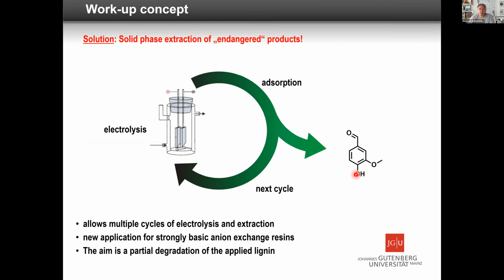The last part is definitely devoted to this. We make a conversion, we have a significantly low conversion. That means, okay, we can go up to 15%, but the problem is there are still some building blocks we have to separate off. And the question is, how can we get the important compounds out of the system without destroying them? Because these compounds are prone to oxidation. And the way is that we have a kind of adsorption, and then we directly go further with that.